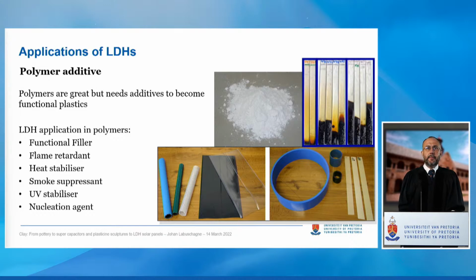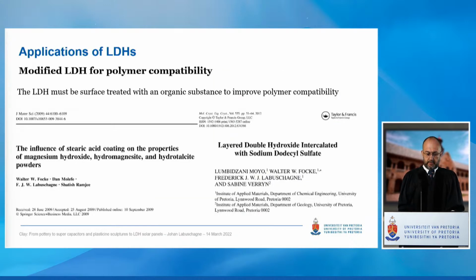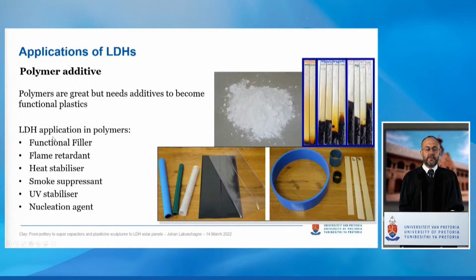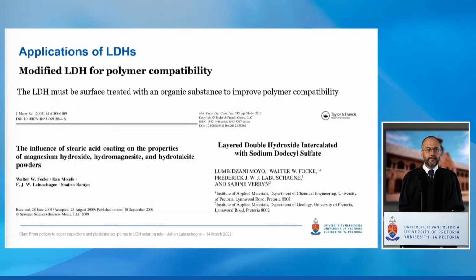I'm only listing the polymer additive functionalities here that we have investigated in my research. And I'll go through examples of all of these during the rest of the presentation. But first, to get the LDH, which is an inorganic material, into polymers, which is an organic material, you typically need to modify it. In these two publications, we first investigated modifying only the surface of the LDH, the one on the left, and then also the complete LDH, where we intercalated a surfactant, an organic surfactant, into the interlayer.